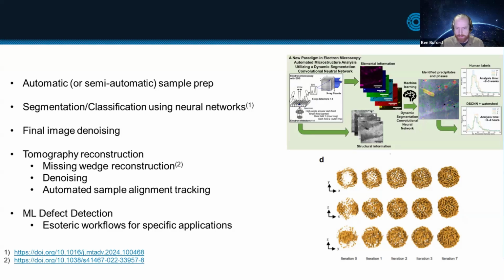I have a plot from another paper in the bottom right here that shows initially that with the missing wedge, you lose a lot of detail, but as you iterate over reconstructing and then regenerating the missing wedges, you can iterate a few times and get a much cleaner and more robust result that you wouldn't have been able to get without AI. Then also there's denoising, where you can denoise either the raw images you get initially, the sinograms, or the final reconstructed slices you're looking at, just to get prettier pictures.